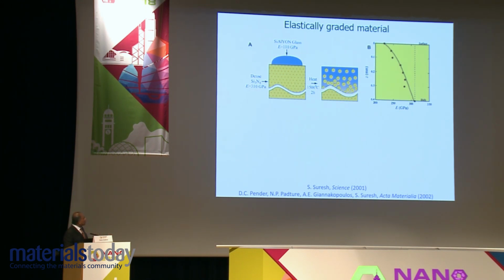Of course, glass has a Young's modulus of 110 GPa, and silicon nitride has a Young's modulus of about 300 GPa. So because of the diffusion, there is a continuous variation of Young's modulus at the surface of 110, about 200 GPa, 220 GPa, because it's part glass, part silicon nitride, to a depth of about 400 micrometers, where the Young's modulus is about 300 GPa. So that's the microstructure that you create.